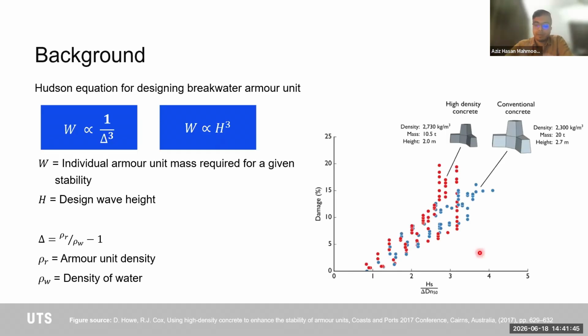So this is a summary of the findings that came out of the UNSW Water Research Lab, where they have correlated the damage that a breakwater sustains to a Hudson number. But the interesting fact to look at here is with conventional concrete with a density of about 2.3 ton per meter cube, even if the mass of the conventional concrete armor unit is downsized to about half, we see a similar level of damage for a typical Hudson number here. So what it means is we can reduce the size of the armor units if we go for a high density concrete. For example, here, this physical model was done with 2.73 ton per meter cube of material density. So this armor unit was made out of a dense material.